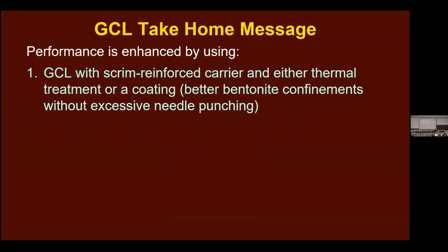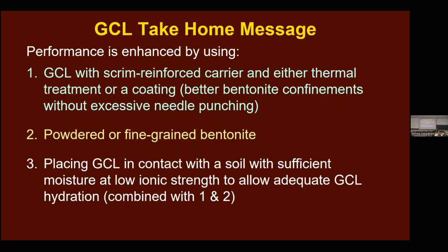So, take-home message here, GCLs with scrim-reinforced carrier and either a thermally treated or coating perform much better because they give better confinement of the bentonite at low stresses. Powdered or fine-grained bentonite is much better than coarse bentonite in situations where you're not going to be fully hydrated. And placing a GCL in contact with a soil with sufficient moisture and low ionic strength to allow it to adequately hydrate before it becomes in contact with a nasty fluid will aid its long-term performance.